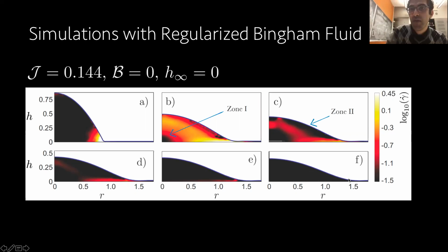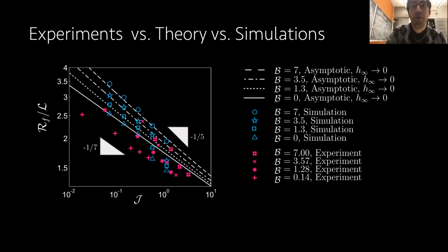So I can get this final radius and put it on the same curve that I showed you before and do the comparison. It's the same comparison curve now with the blue symbols that are the simulations. So here I have simulations, asymptotic solution, and experiments, all of them together. Again, the scaling seems to be fine, at least for low J numbers. But now I can see some discrepancy again. We have our guess where the discrepancy comes from. We can discuss it at the end of the talk.